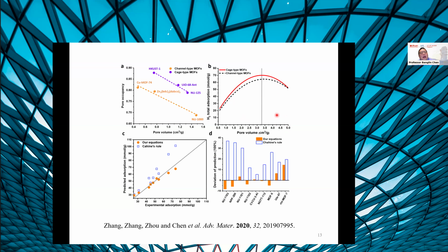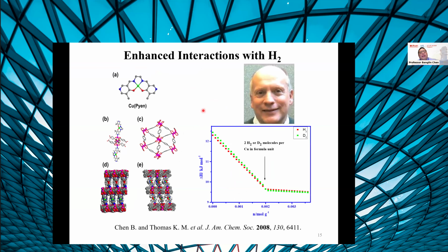So the challenge is how to enhance the hydrogen interaction with the MOF material. Because the higher the interaction with hydrogen means higher temperature for hydrogen storage. Because of that, we thought we might use metal ligand because this metal site might potentially have stronger interaction with hydrogen molecule. And we construct this mixed metal organic framework, and indeed, the interaction with hydrogen is higher, over 12 kilojoule per mole, and typically those MOF material only have 7 to 8 kilojoule per mole enthalpy.